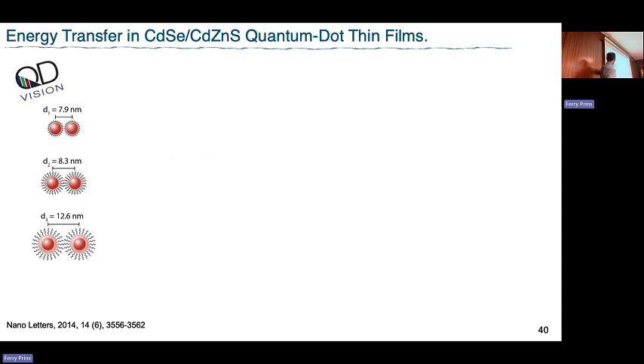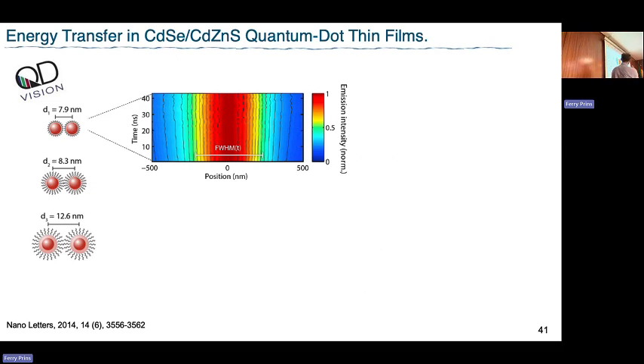So it's the same kind of particle, but now we are going from 7.9 to 8.3 to 12.6. And we have this system, and we have a film, and we can study how the transport is different in each one of these films. So we can do our measurements. It's very subtle in this case, but you can see that it's broadening as a function of time. For that maximum, it's increasing as a function of time.